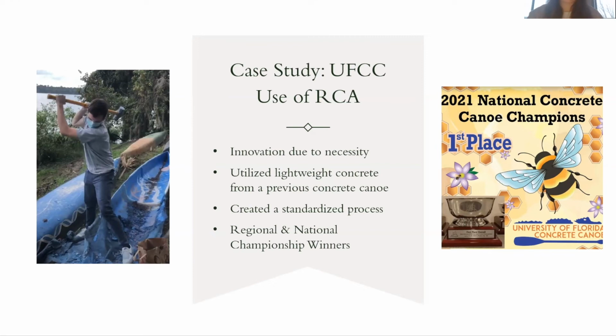The material that passed the number 100 sieve was safely disposed of, and the material that was retained on the number 4 sieve and higher was then repulverized and then sieved again. Alongside creating a standardized process to obtain consistent RCA for use in our concrete canoe mix design, our team wrote a material and testing data sheet composed of the data that we had compiled from our standardized testing procedures in order for our aggregate to be compliant with the rules. All of our hard work paid off when we won both the Southeast Regional Championship as well as the National Concrete Canoe Championship in June of 2021.